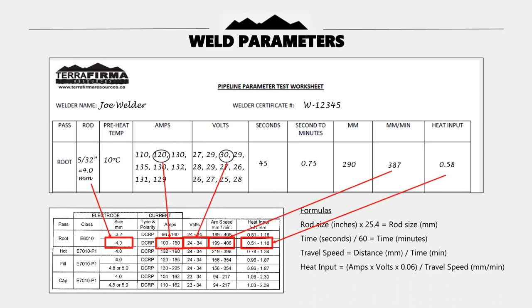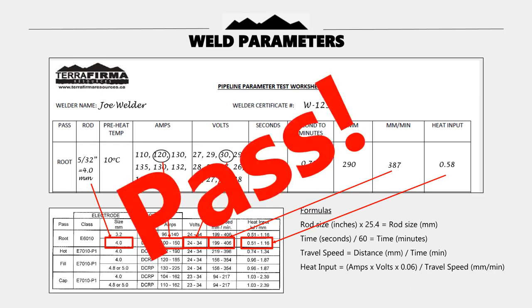Look in the line beside root and 4.0 mm rod size. 120 amps falls within the range of 100 to 150, so it passes. 30 volts falls within the range of 24 to 34, so it passes also. 387 millimeters per minute falls within the range of 199 to 406, so it also passed. Lastly, 0.58 kilojoules per millimeter falls within the range of 0.51 to 1.16, so it passes also. So, did the welder pass based on these parameters? Yes, they did. You will need to complete this process again for the hot pass, fill, and cap to fully qualify the welder to the WPS being used.